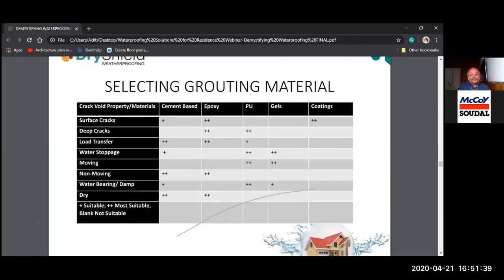This is a chart for selecting your grouting materials. For surface cracks, you use cement. These are suitable, and epoxies are very good where the cracks are very wide. Epoxy can be used there. And where the cracks are narrow, you can use coatings. Coating maybe below 0.5 mm, below 1 mm also. Coatings will be good. And for deep cracks, epoxy and polyurethanes.